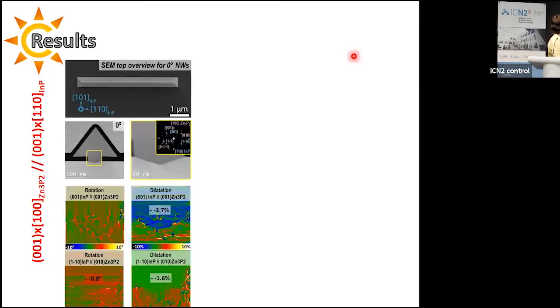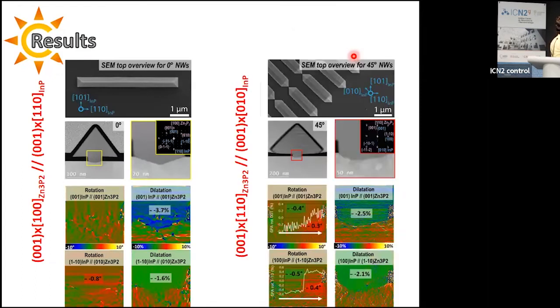In particular, we selected two orientations. The first one is where the 100 of zinc phosphide is parallel to the 110 of indium phosphide. And the second one is when the 110 of zinc phosphide is parallel to the 010 direction of the indium phosphide.